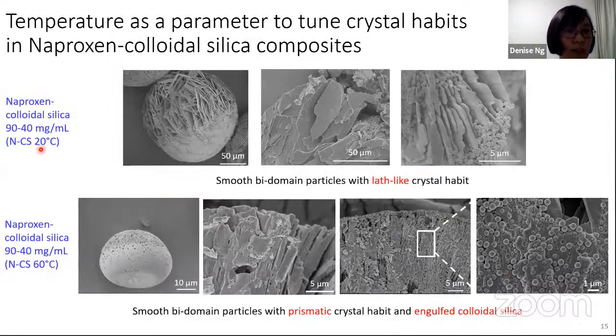Next, we also varied temperature to see if it will influence the crystal outcomes. So here in the case of 20 degrees, which as we saw earlier, it formed a bi-domain. When we increase the temperature, it also likewise formed a bi-domain particle as well. However, what's interesting is that across the two temperatures, at the lower temperature of 20 degrees, it forms a lath-like crystal habit, whereas in the case of a higher temperature, it forms a prismatic crystal habit.